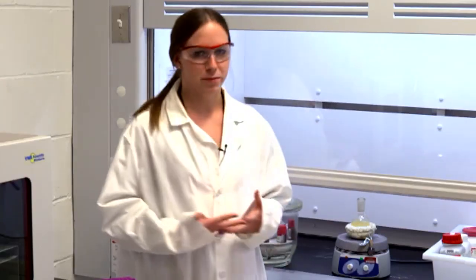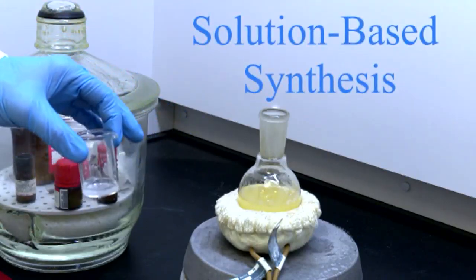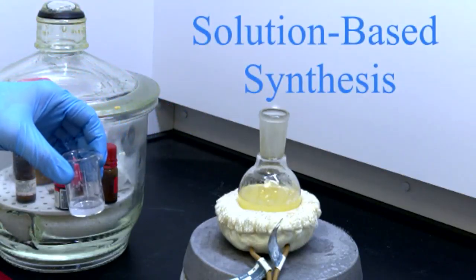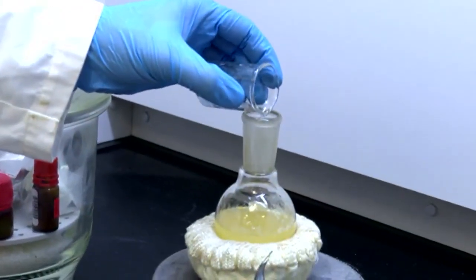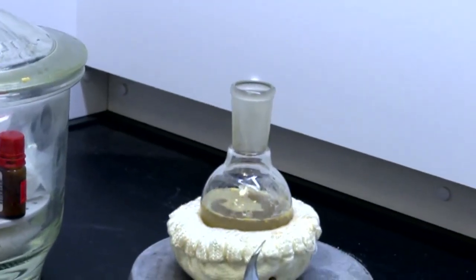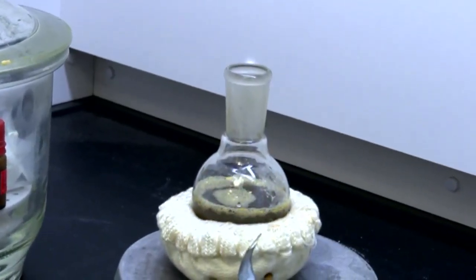Today, I'm synthesizing platinum nanowires using this soft template technique in order to create a nanowire network. Specifically, I added a platinum precursor solution in with a combination of CTAB, chloroform, and water. And after about 30 minutes, I will add a sodium borohydride solution, the reducing agent, in order to actually form the platinum nanowires within the inverse micelle network.